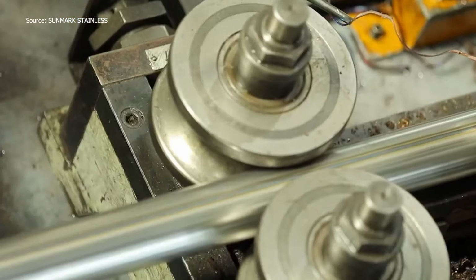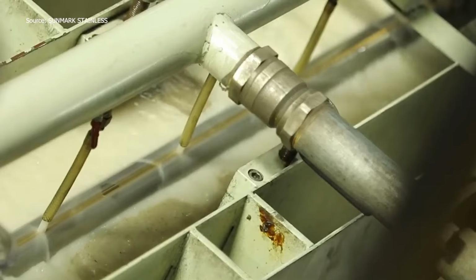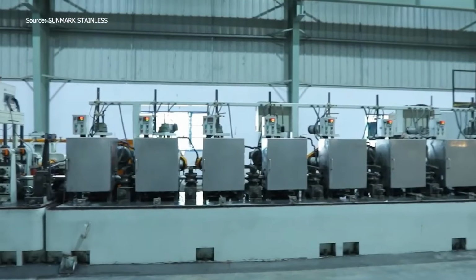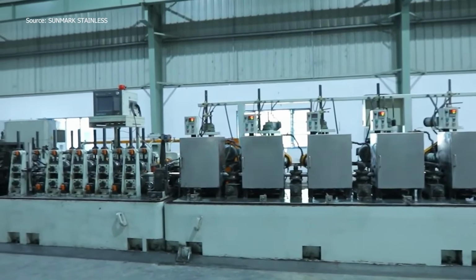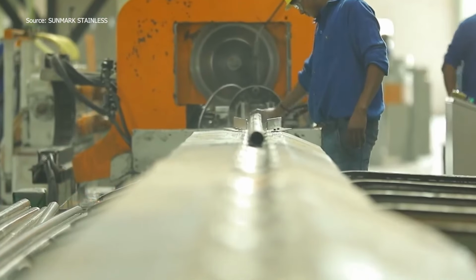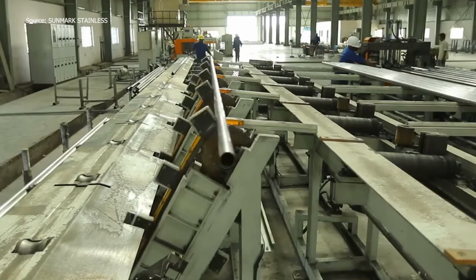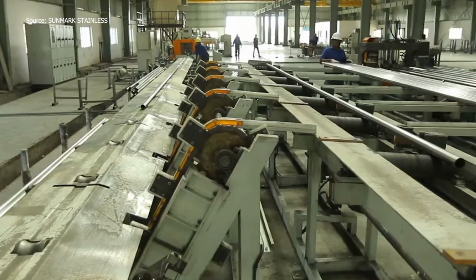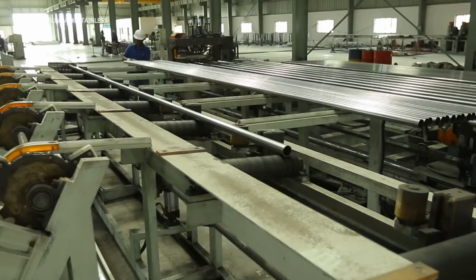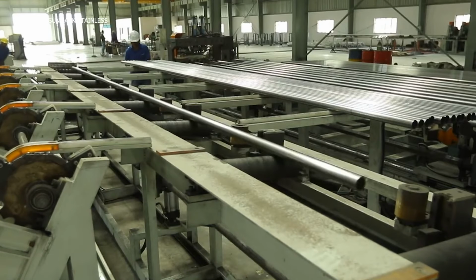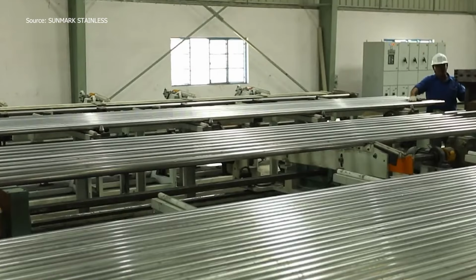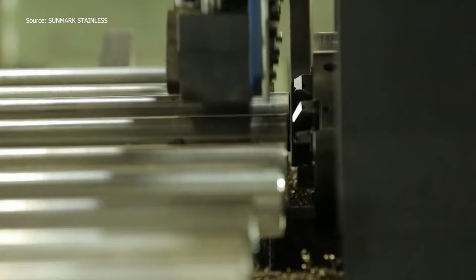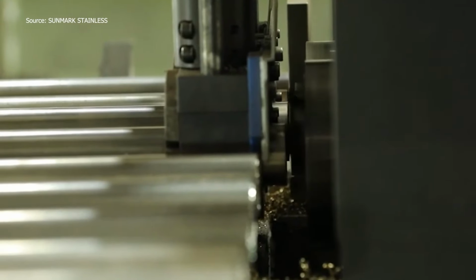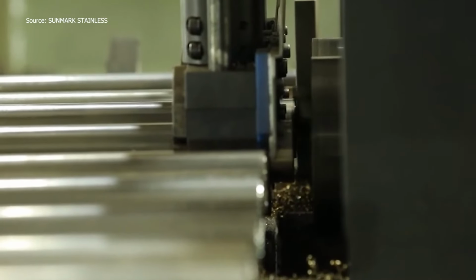The welded seam undergoes bead rolling and scarfing, removing any excess material to create a smooth inner and outer surface. Tubes then pass through sizing and straightening sections to achieve the exact outer diameter, ranging from 19.05 mm to 76.20 mm, with thickness between 0.9 and 2.5 mm. Automatic cutoff machines trim each tube to lengths from 3 to 6.2 meters. There's something satisfying in knowing each cut translates to dimensional perfection, tuned by machines built for reliability.